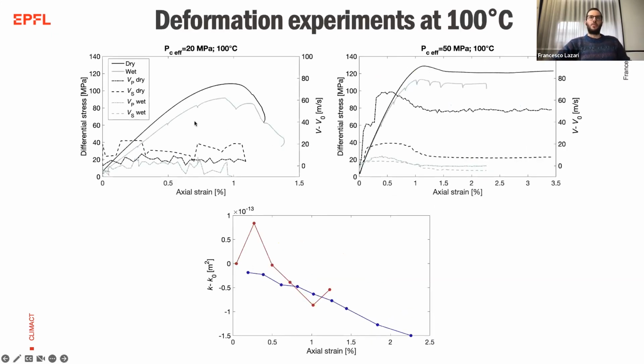Here are a few details of the experiments at 100 degrees. Here I'm going to show you a wet and a dry experiment in the first panel done at 20 megapascal of confinement pressure, where the sample was brittle, so it was breaking with a fracture. And on the second panel, there are two experiments done at 50 megapascal of confinement pressure, where the samples were ductile, meaning that they were not breaking, but they were deforming homogeneously.